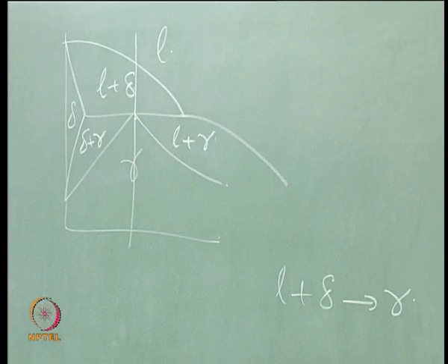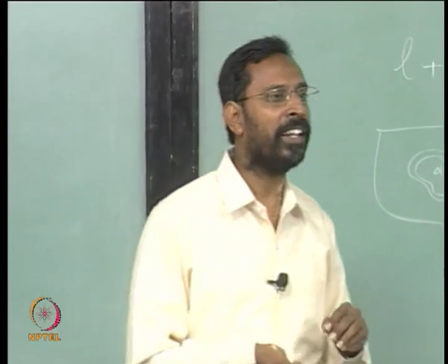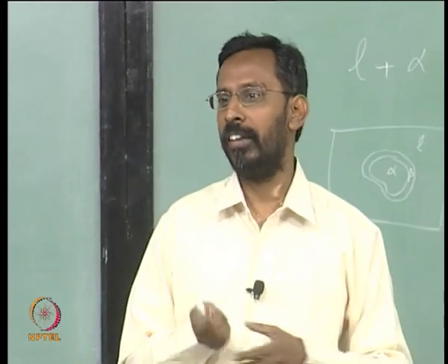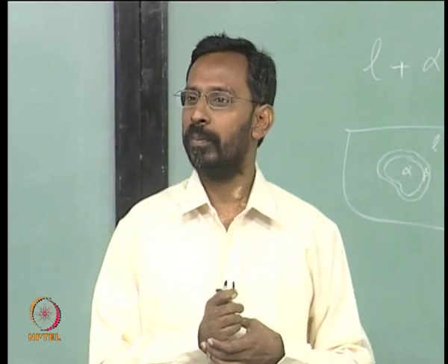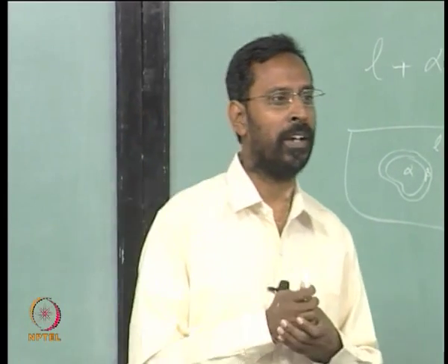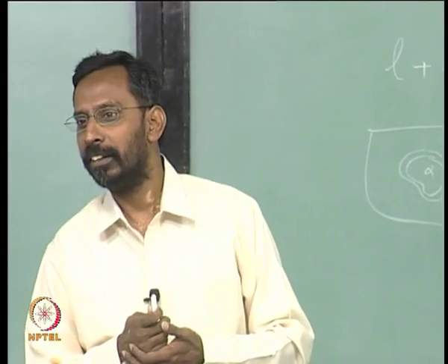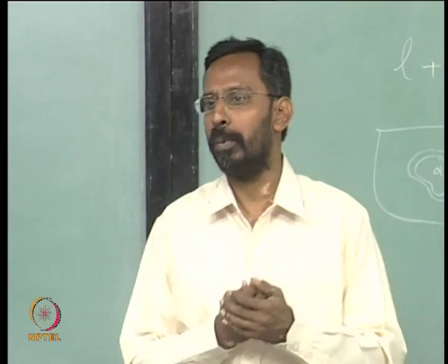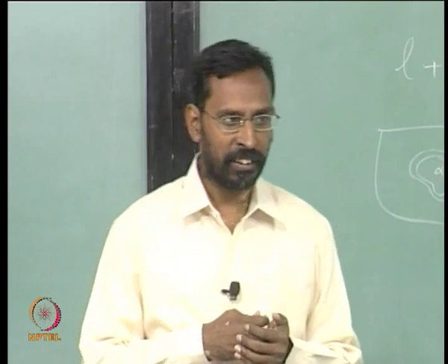A phase diagram cannot talk about volume fraction, because in a phase diagram the x axis is basically the weight fraction of x, or atomic fraction of x. So, volume does not come into the picture. How do you get then the volume fraction of a phase? By using the density. If I have a two phase mixture and I do microscopy, what fraction do I get?